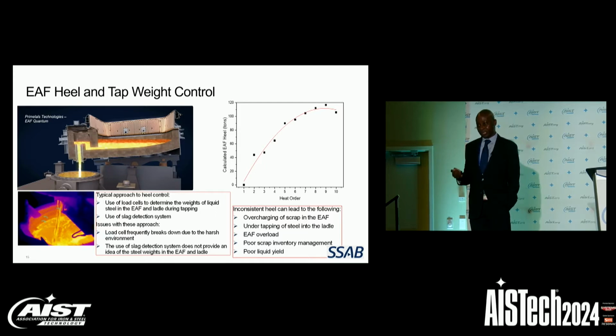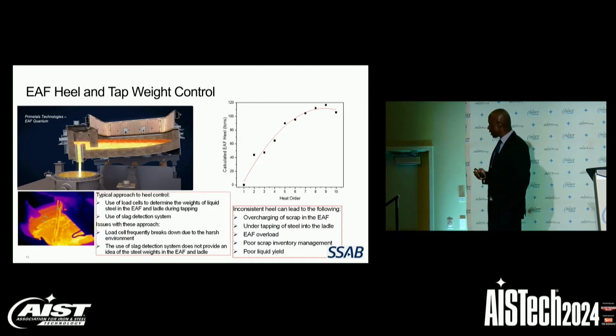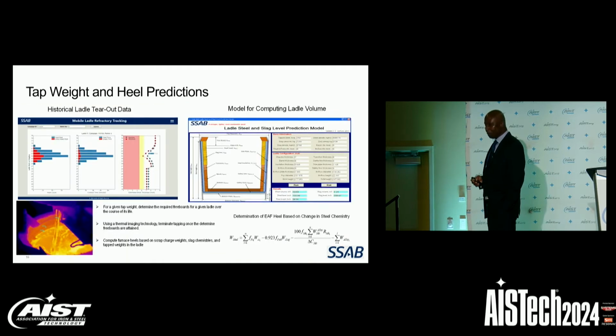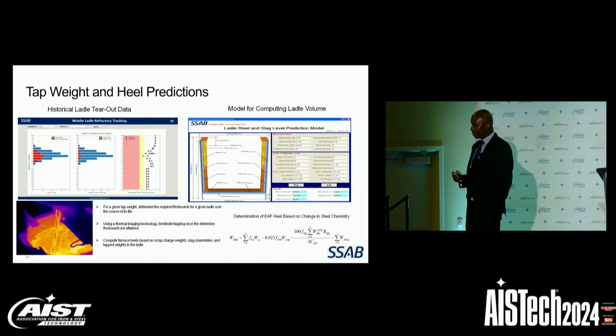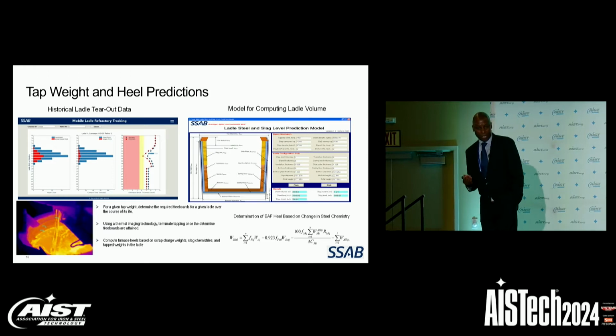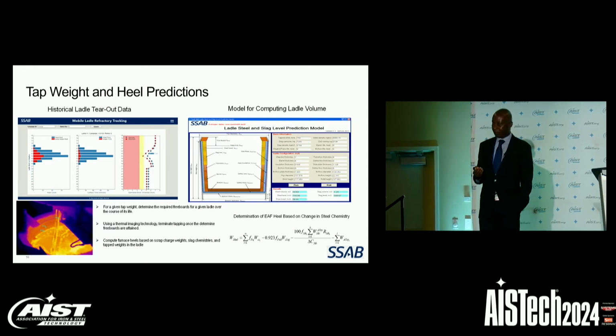So inconsistent heel can lead to overcharging of scrap in the electrical furnace, undertapping of liquid steel into the ladle, EAF overload, poor scrap inventory management, and poor yield. As a solution, we decided to develop a model to predict tap weight and heel in the electrical furnace.